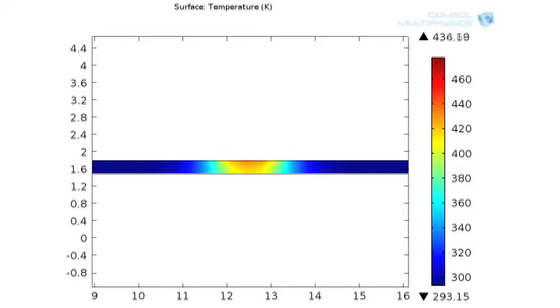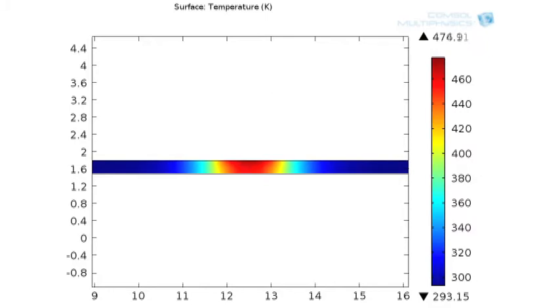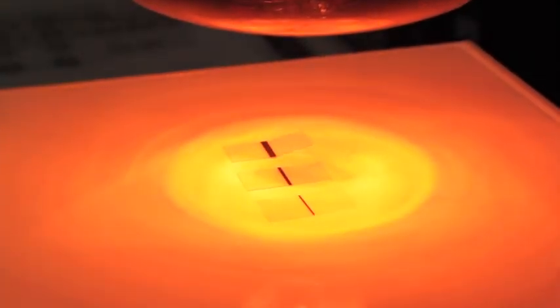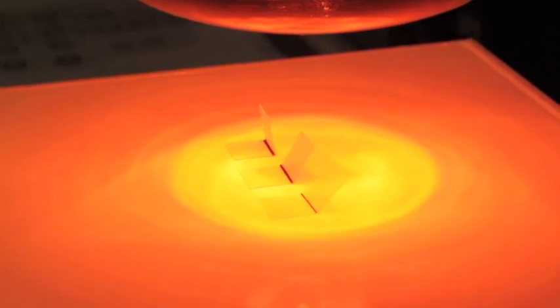With time, the temperature in the sheet underneath the ink increases progressively deeper into the sheet, as well as in areas outside the inked regions. When the temperature inside the film exceeds a certain critical value, the stored strain gets released, which causes the sheet to shrink.